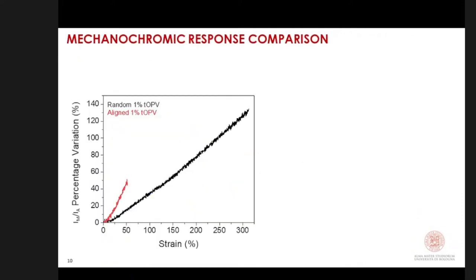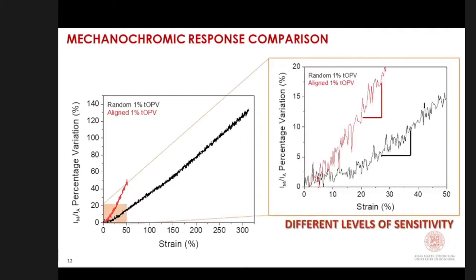But if we compare the percentage variation of the two samples, we can observe that the slopes are very different. In particular, that of the aligned mat is much, much greater than that of the random one. Especially if we observe the low strain values, we can see that at the same value of strain, the response of the aligned mat is 3 times that of the random one. And this results in a very different level of sensitivity of the two samples. In particular, the aligned one is more sensitive with respect to the random one.